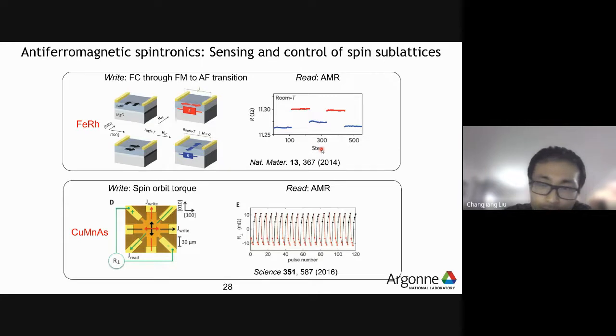So then people use the anisotropic magnetic resistance in the antiferromagnetic phase to read out the direction of the Néel axis. Basically, the high and low resistance corresponds to different orientation of the Néel axis.